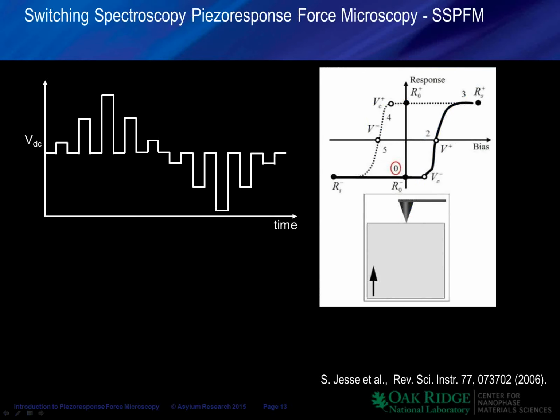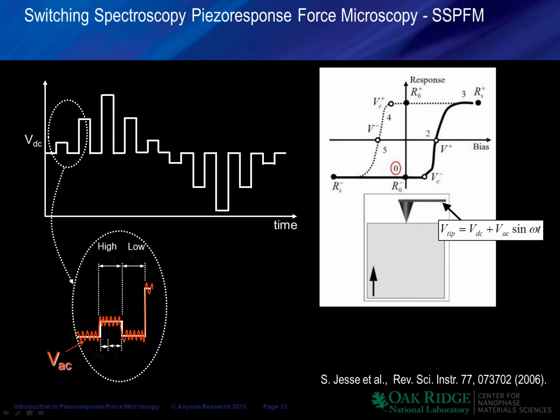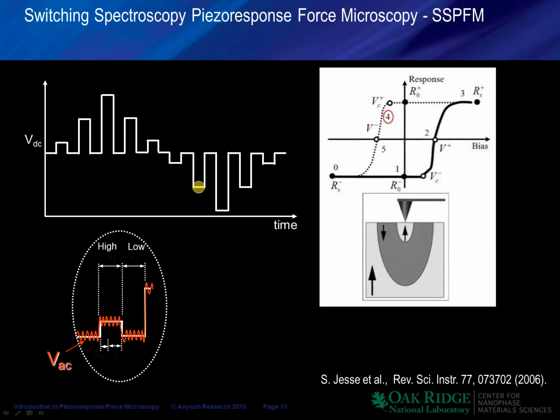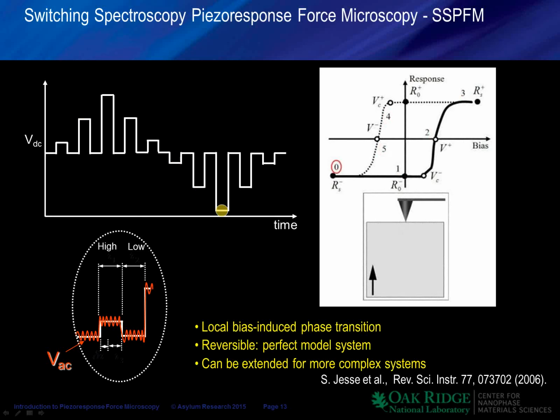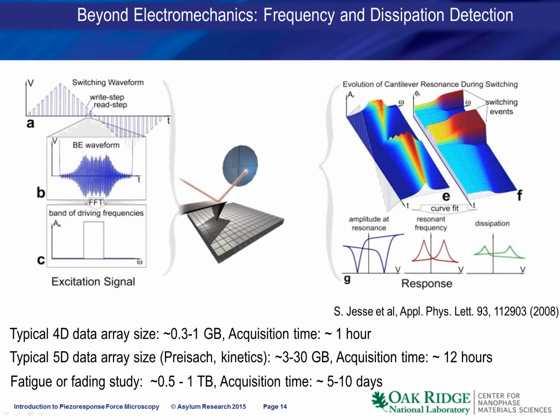So obviously let's start with the four-dimensional imaging. In this case we can start with our switching spectroscopy PFM. So we have this rectangular waveform which is modulated, and then we apply sinusoidal modulation on top of it. The same way as I described a few minutes ago. However, now we are going to use band excitation rather than sinusoidal wave excitation. And in order to do it, we actually implement the four-dimensional measurements.